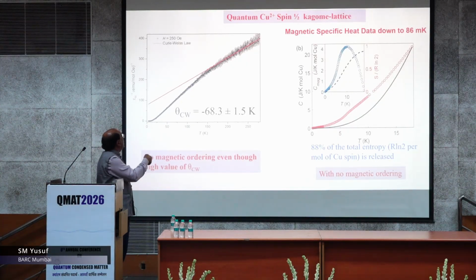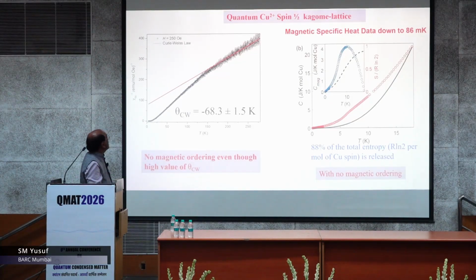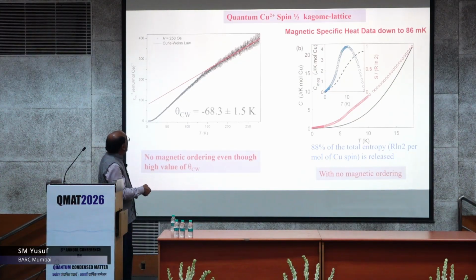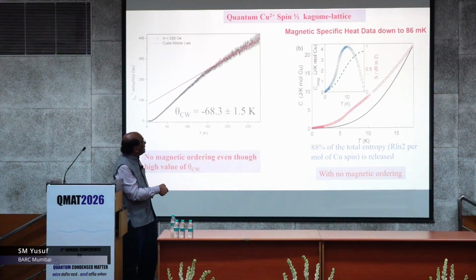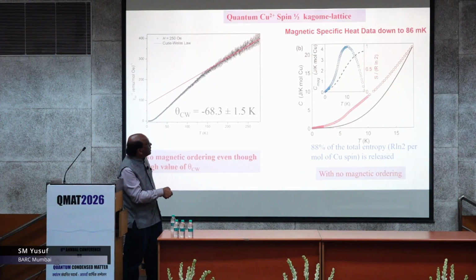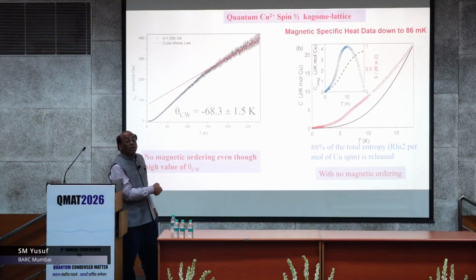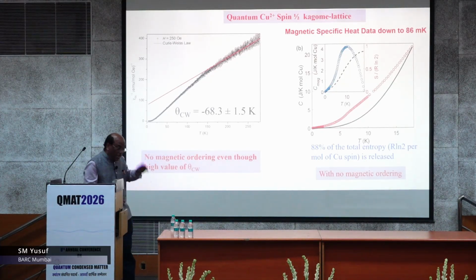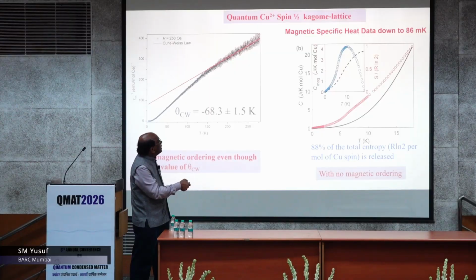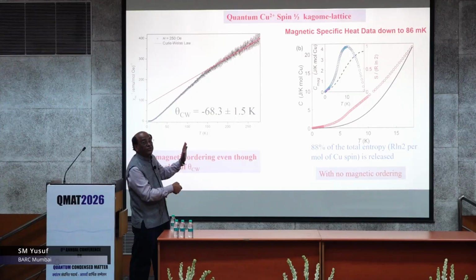By the way, this sample was prepared in JNCASR, Professor Tapas Maji's lab, and then when we do this magnetic entropy measurement, so this is my lattice part, this is my measured, and the magnetic part is this, down to 86 millikelvin, which we did that time in Professor S.K. Dhar's TIFR lab, down to 86 millikelvin. And what you see here, down to 86 millikelvin, first of all, we do not see any magnetic phase transition, and what you also see, the 88% entropy of this copper spin is released down to 86 millikelvin,